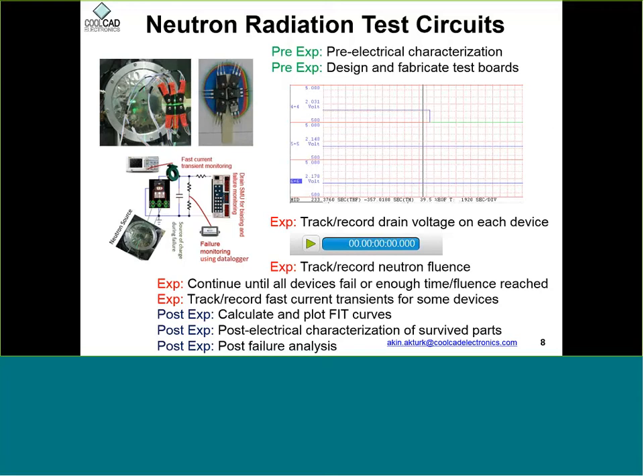And you can also see our circuit. What we do is during the whole experiment, you monitor the drain voltage on the device. The gate is shorted to source, and most of the time you increase the drain bias, so it's in blocking state. Then we continuously monitor the drain bias during the whole length of the experiment. And when the device fails, the drain bias goes to 0, as you can see on the right. And then we also record the number of neutrons that caused that particular device to fail.